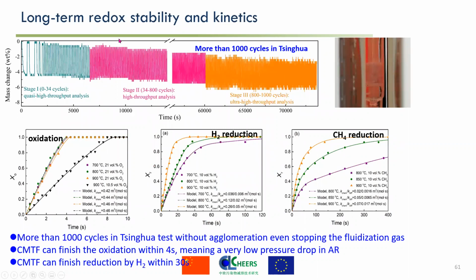Firstly, we carried out a long-term redox stability experiment for CMTF. Totally 1,000 cycles were conducted. CMTF has no decay in reactivity and low agglomeration during the whole test. Even if we stop the gas supply, there is no agglomeration. Then, CMTF has a very fast oxidation rate. It just needs 4 seconds to finish the oxidation. That means the required residence time and bed inventory in the air reactor is very low, so the pressure drop in the air reactor is also very low.